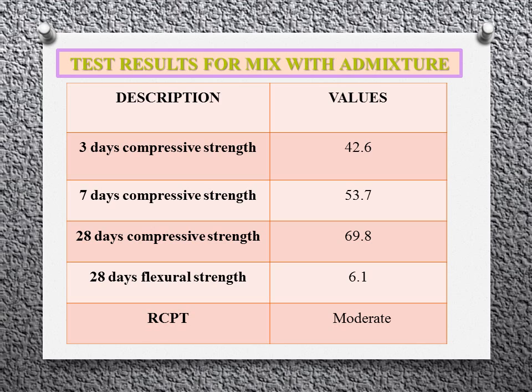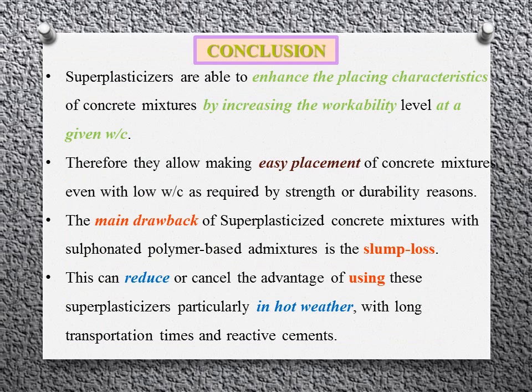Thus, the values obtained for the compressive, flexural and RCPT tests are higher for the mix with admixture compared to the control. Thus, we conclude that superplasticizers are able to enhance the placing characteristics by increasing the workability at a given water cement ratio. Therefore, they allow easy placement of concrete mixes even with low water cement ratio as required by strength and durability reasons. The main drawback is its slump loss. This can reduce or cancel the advantage of using superplasticizers, particularly in very hot weather.